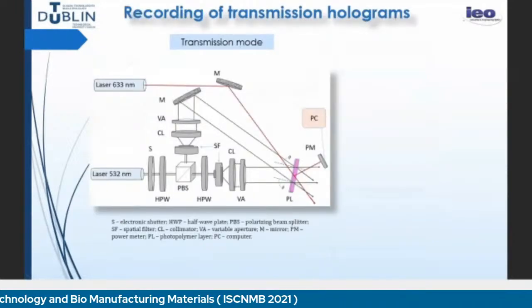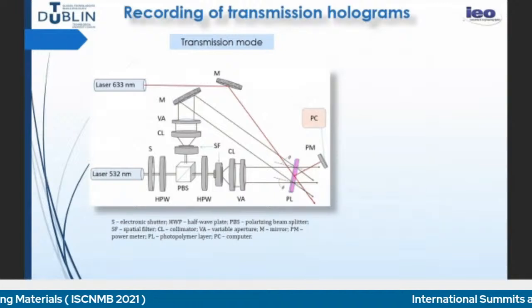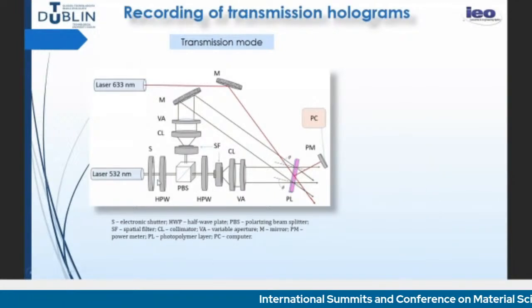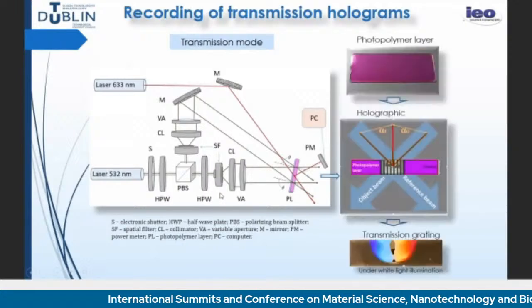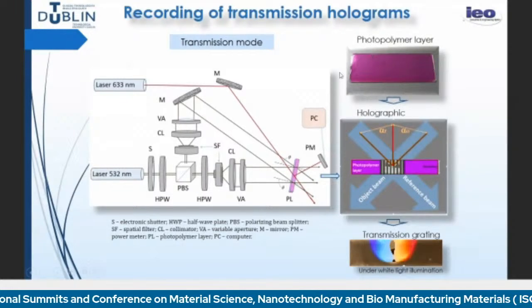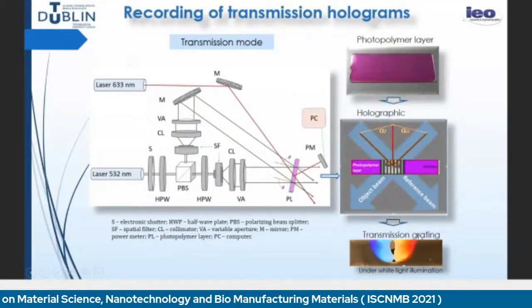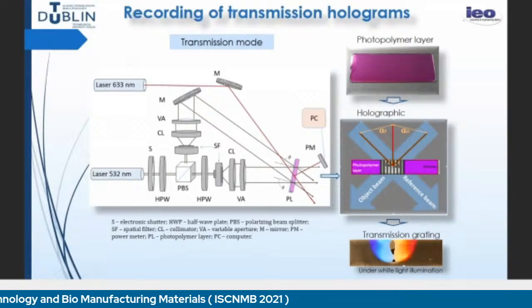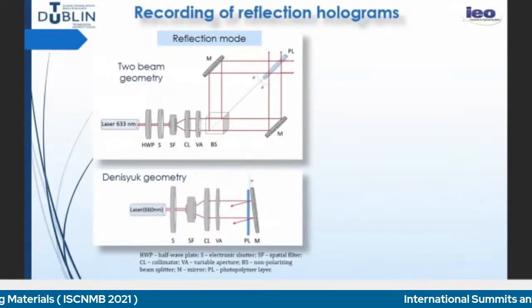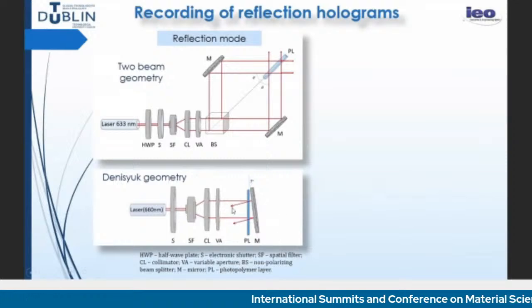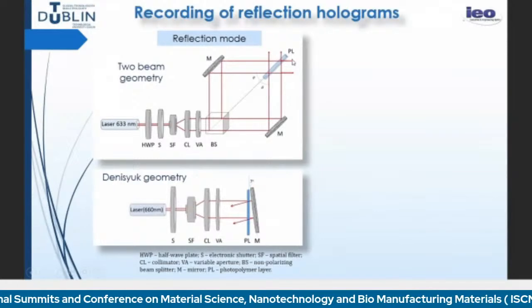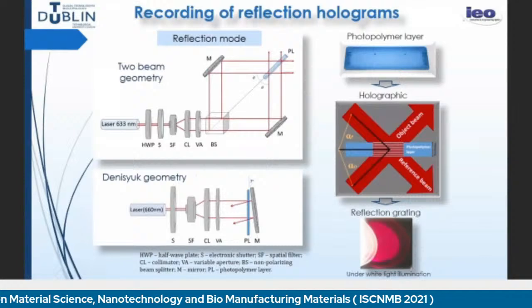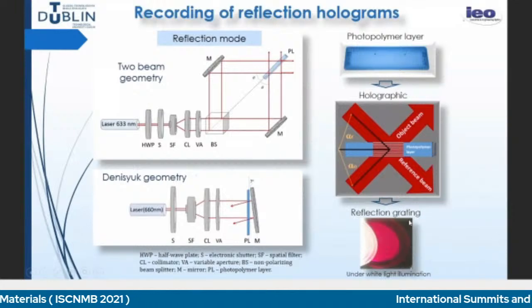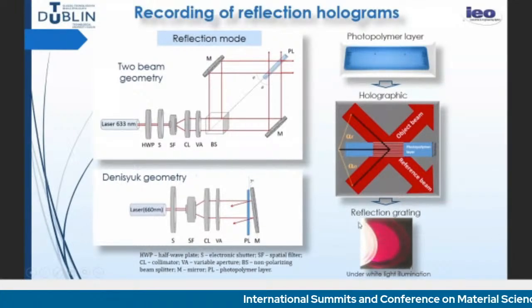These are the setups that we use to record transmission holograms. It's a standard two-beam holographic setup with polarization control of the two beams and also intensity control of the two beams. And this is a typical layer used to record in green. And this is a photograph of the transmission grating recorded in this material. In reflection mode, we use two setups: a two-beam recording setup and Denisyuk mode. This is more for objects, and this is where we want very accurate control of the intensity of the two beams and to obtain maximum visibility of the fringes. And this is an example of a photopolymer layer sensitive in the red, and this is a reflection hologram. This is actually a mirror, and we have illuminated it with white light.